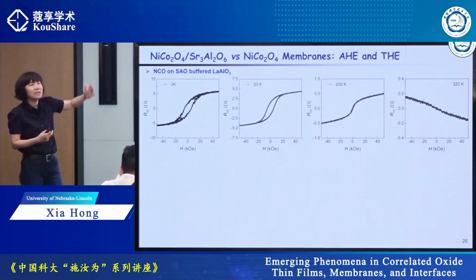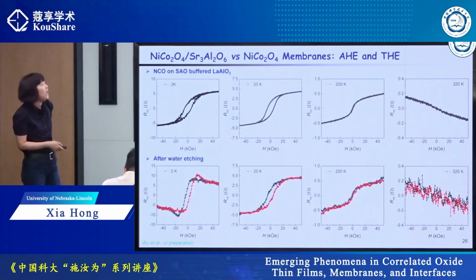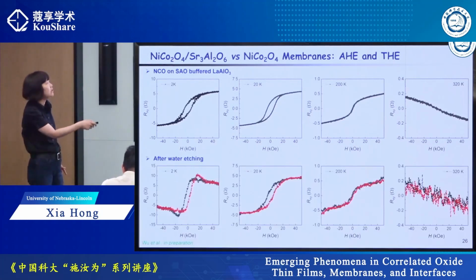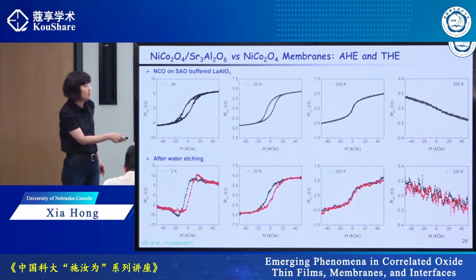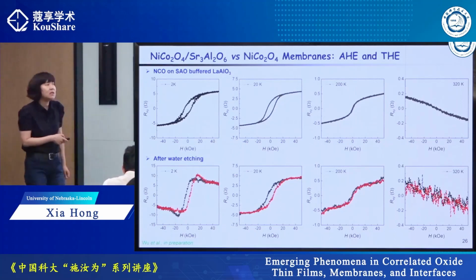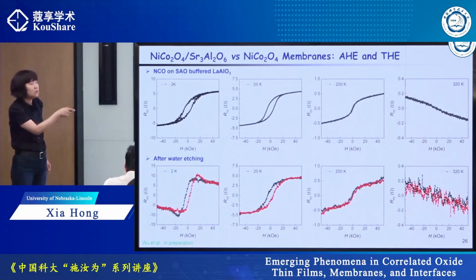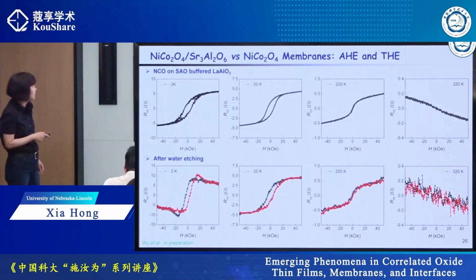The magnetic easy axis is not perpendicular nor in plane. Now we water etch it. At high temperature, everything looks very similar. We have similar Curie temperature, similar sign change temperature, similar amplitude of the anomalous resistance.